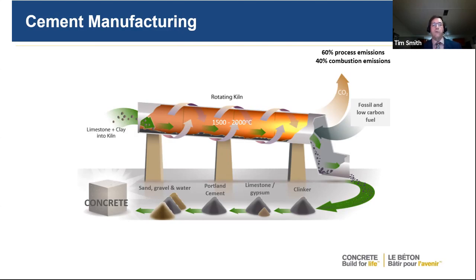Because this goes up from only up to 5% to up to 15%. So that's the difference. There's no difference in the process here. For the clinker, 60% of the process emissions is the CO2 being driven off, and 40% is the combustion. So the issue becomes how much limestone is being ground up with the clinker. In GU, it's only 5%. In GUL, it's actually up to 15%.